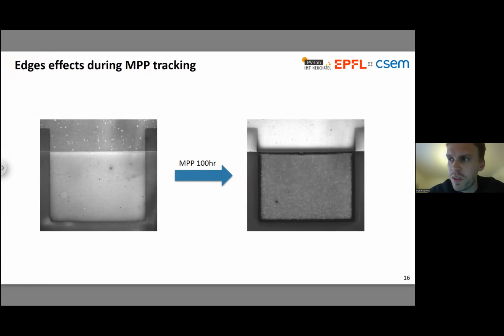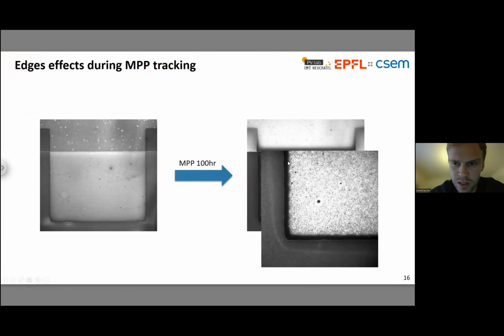So one of the first things that I wanted to test as soon as I started seeing these patterns is, do we see them in MPP tracking? And the answer is yes. So here I'm showing a cell before and after it was MPP tracked for 100 hours under one sun illumination, and you can clearly see this pattern of modulated PL intensity around the cell boundary. So here around the silver boundary, with this curious little front occurring around the corner.